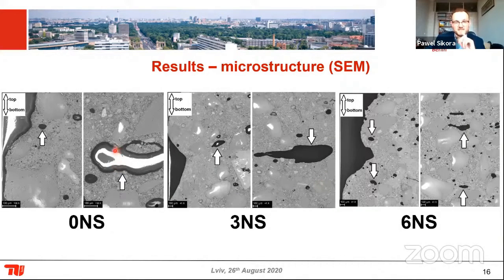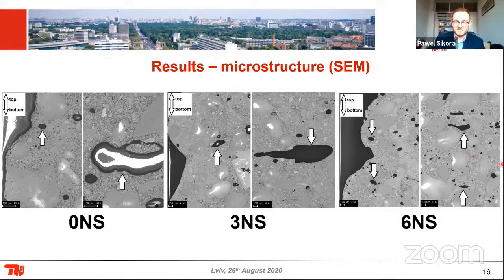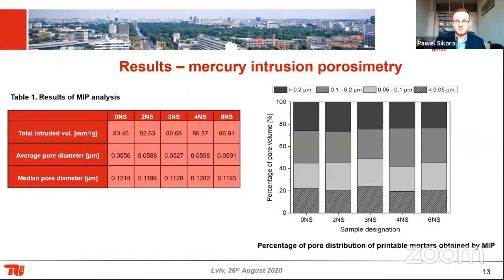Here are SEM images of the concrete element. We can see elongated flat pores which occurred during printing. In specimens containing a certain amount of nanosilica, we also find them, but we also see many more spherical pores, which are beneficial. However, when we exceed the amount of nanosilica, we observe increased porosity. This most probably happens because if we add too much nanosilica, the rheological properties — specifically shear stress — become too high, causing problems with extruding these elements and resulting in air intrusion into the mixture. This means voids are formed in the specimen, which most probably results in decreased compressive strength, consistent with the compressive strength results and MIP analysis.